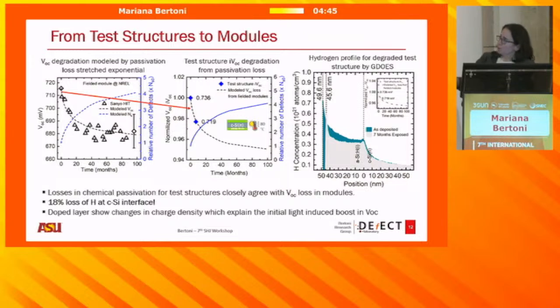So we take a look at the stacks, and the first thing that we observe is that we have a fair amount of hydrogen that is leaving the interface. These are glow discharge optical emission spectroscopy measurements. The as deposited is the green. The 7-month exposed is the gray, and you can of course do this measurement after several months and even a year, and the drop is very sharp at the very beginning, but then it plateaus.